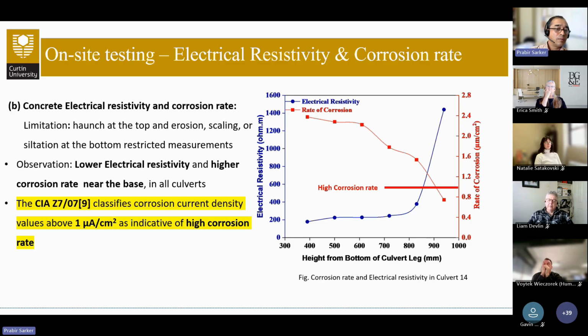The CIA Z7/07 practice note, Concrete Institute of Australia, classifies corrosion current density values above 1 microampere per centimeter square as indicative of high corrosion. You can see indication of high corrosion in some of the culverts - this is culvert number 14. It was different because we investigated only 3 culverts in this stage, so this is one of the culverts.